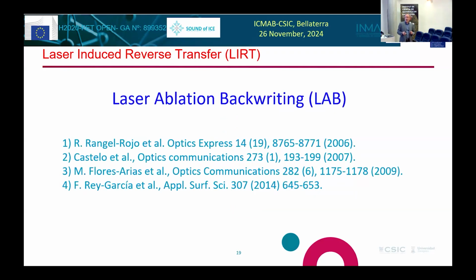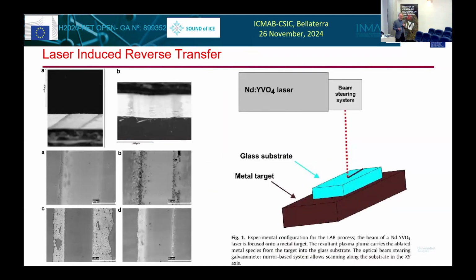And this is just something we did in collaboration with a group in Grenoble, which is CNRS, in LMGP, and David Muñoz is the professor of research there. And what we did is combine SALD, spatial atomic layer deposition, with laser processing. The idea in this project was to crystallize selectively the deposits that he made with SALD, which are amorphous. And we did that for copper oxide and zinc oxide because they're semiconductors and they're very interesting for some solar applications.